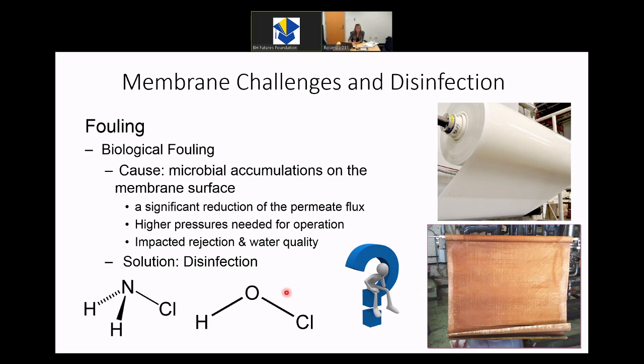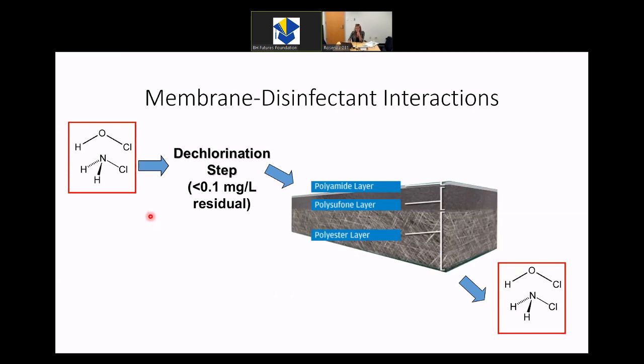So what do we do to avoid this issue and maintain the integrity of membranes? One solution, the most common solution, is disinfection prior to the membrane with either chlorine or chloramine. So that's the bridge for why the disinfection byproducts that I was talking about earlier would be relevant. If you are disinfecting prior to a membrane, disinfectants can damage that polyamide layer, that very thin top layer of the membrane.